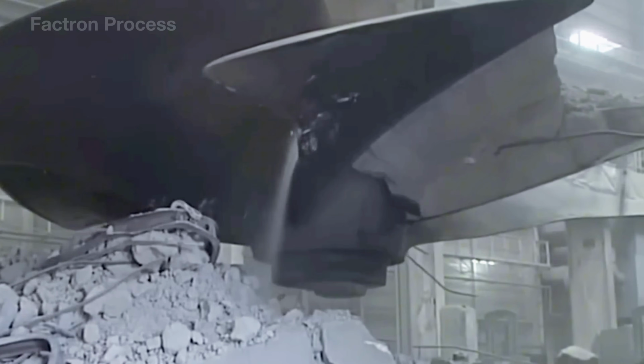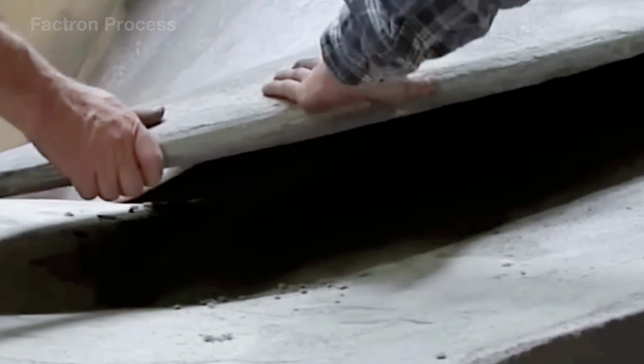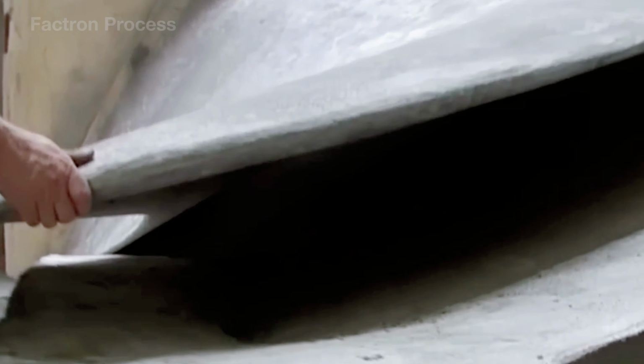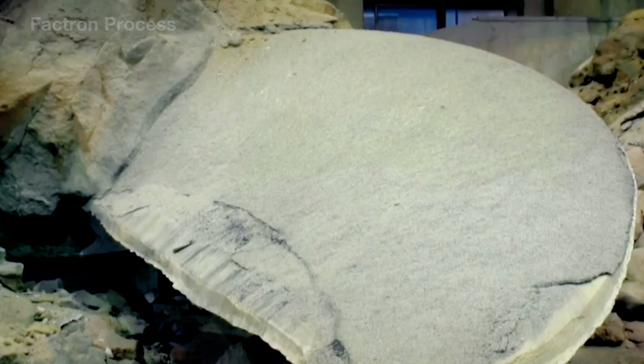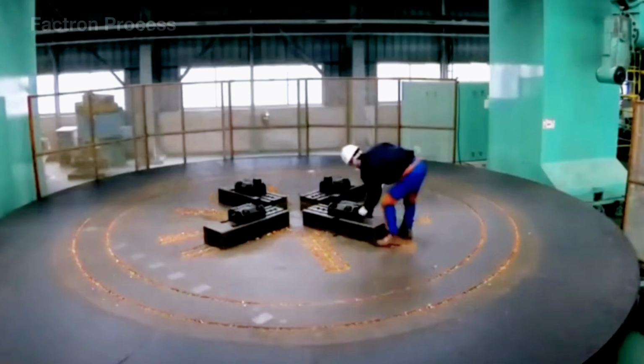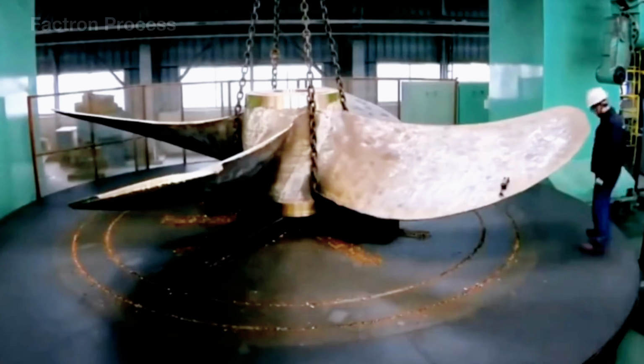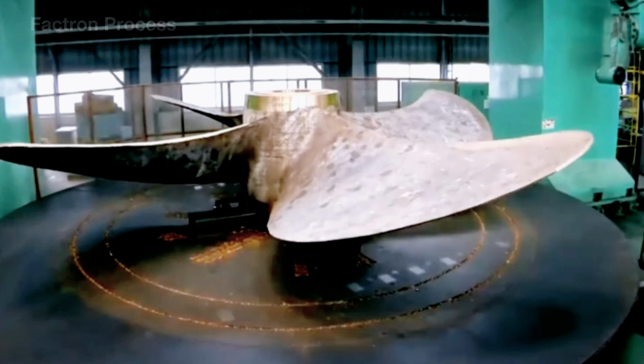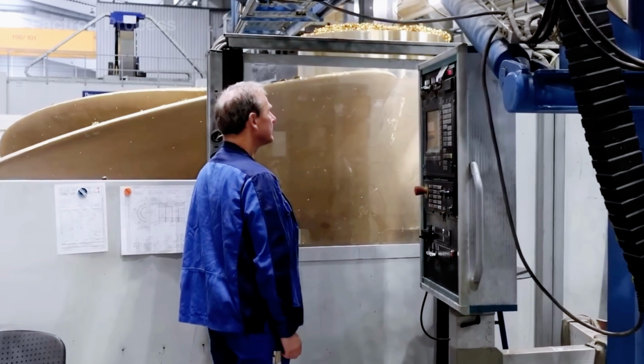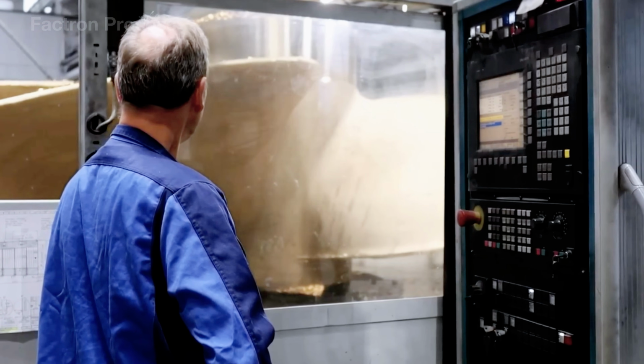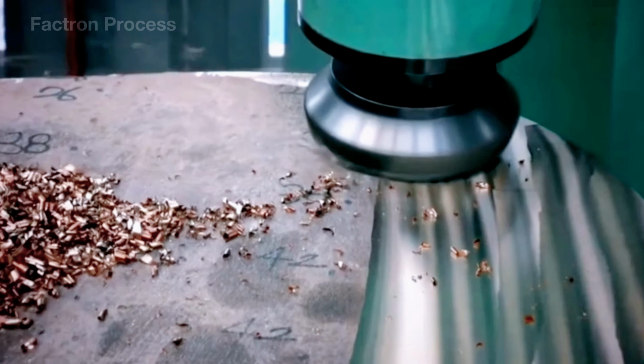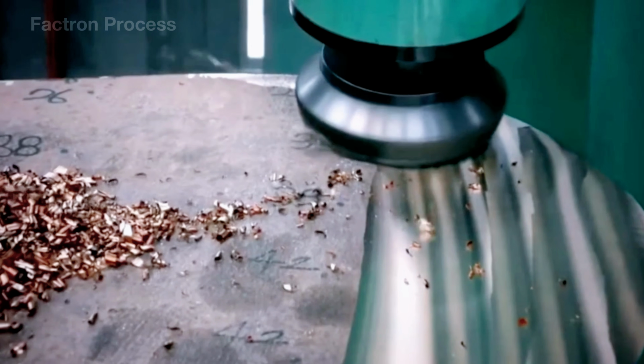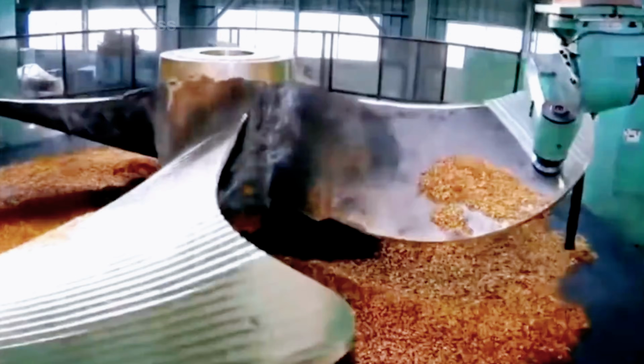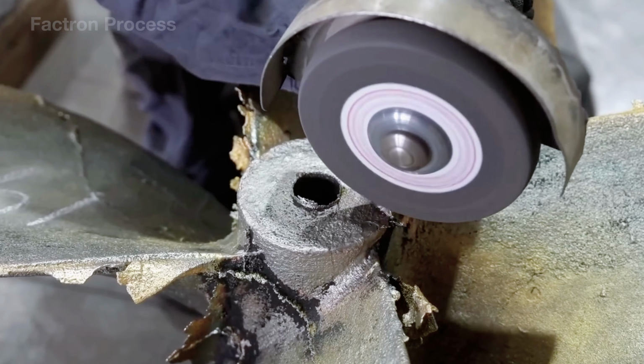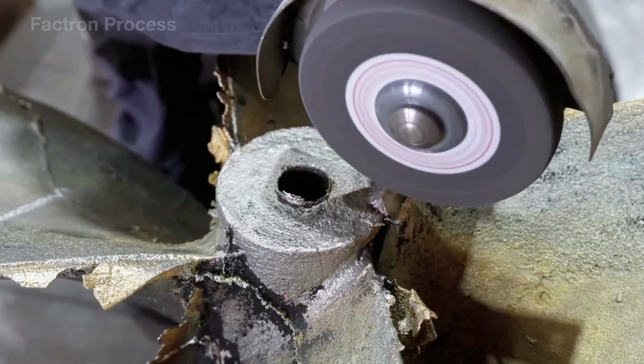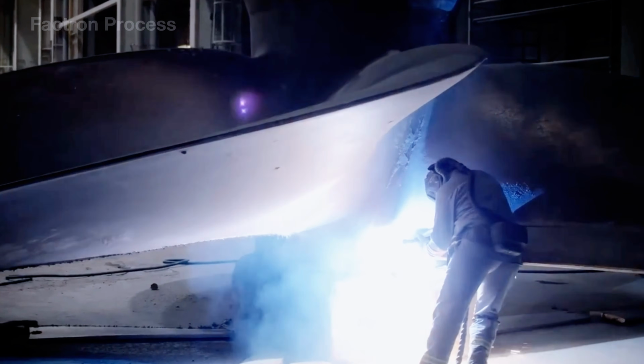When the mold is removed, the propeller emerges beneath layers of burned sand, black oxide, and excess metal around the hub. An overhead crane moves the casting to the cleaning area, where pneumatic hammers and vibrating equipment dislodge sand between the blades. The solidified pouring channels are cut away with industrial saws and ground smooth. Finally, abrasive blasting at around 80 to 100 psi removes the rough black layer, revealing the alloy surface and defects such as cracks, cavities, or unevenly cast areas.